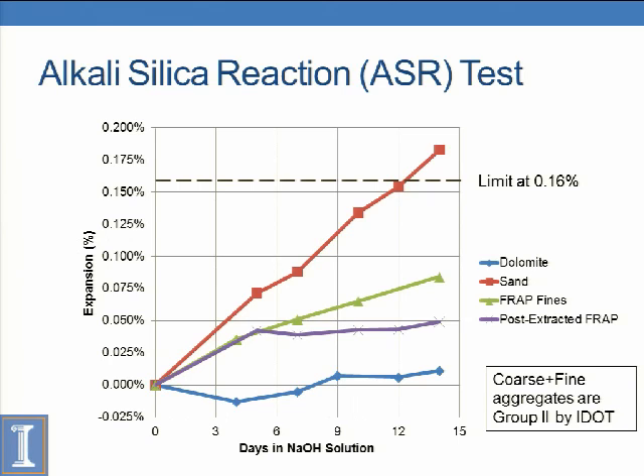Now, this is another durability test, for alkali-silica reaction. Alkali-silica reaction occurs between reactive silica in your aggregates and the pore solution in concrete. Pore solution in concrete has a pH of, say, 13 or so. It's very alkaline. And at that range, you can have a reaction between those alkalis and silica, which is usually your fine aggregate, and you'll form an expansive gel. You'll get very high cracking with that. So you want to avoid, of course, alkali-silica reaction in your concrete.